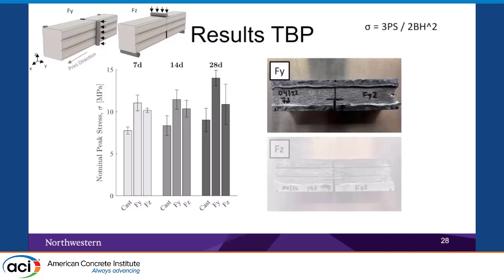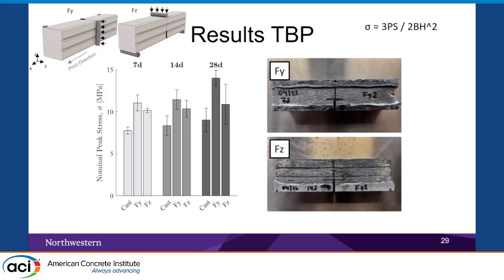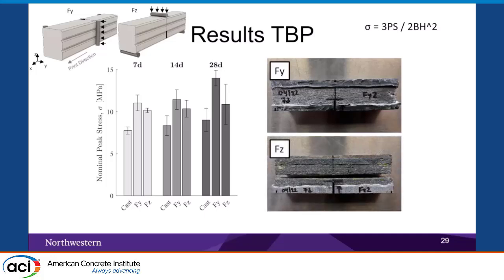The interesting thing here is we have a separation in the layer. Here you can see a separation in the first layer of the printed 3 layers, and that motivated us to start a new experimental program where we can quantify and enhance the interlayer properties using different methods. That's what we are working on right now.